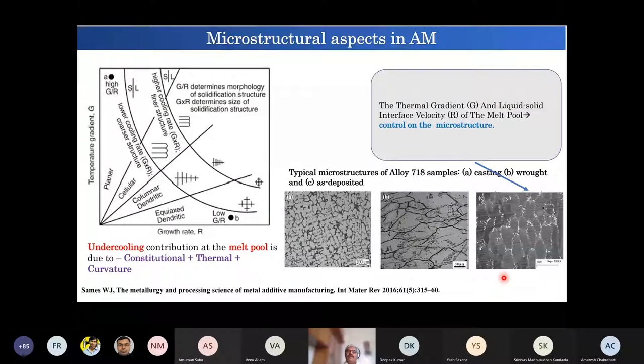Now, the most important thing for which metallurgists have jumped into this process is the microstructural aspects. So additively manufactured materials lead to very characteristic microstructures, which are not so often seen in cast and wrought products. For example, here I am showing the alloy 718, Inconel 718, which is a very favorite alloy for additive manufacturing. These alloys have been well known for several decades, developed from the Second World War onwards. In the cast condition, we get a dendritic structure. Then in the wrought condition, we get grains in a certain elongated or equiaxed manner.